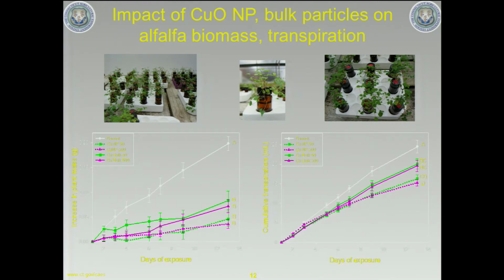In fact, with copper oxide, the data we have is not presented here. We did not put in the whole data. As we change the concentration, what would you expect? If you increase the copper oxide more and more, your toxicity should increase. But what we observed was that we get to a certain extreme, and then if we increase the concentration, after a certain point the toxicity in fact decreases.